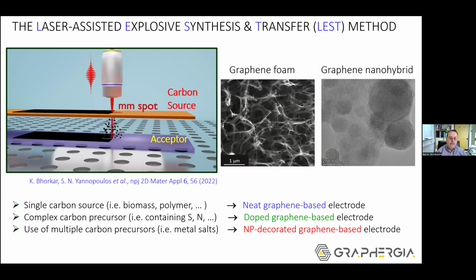In our lab, we have developed, and protected by international patent, a new method to prepare graphene, which is not adhered on the Kapton substrate, but graphene which is at the same time produced and transferred on an acceptor substrate. This last method, laser-assisted explosive synthesis and transfer, is very versatile because we avoid the manual transfer of graphene, which is grown, for example, on Kapton, for using on another substrate, and we can directly deposit high quality graphene on the substrate of interest.